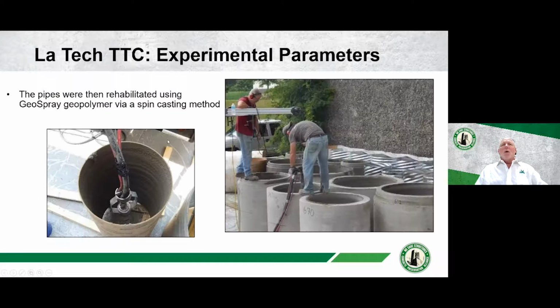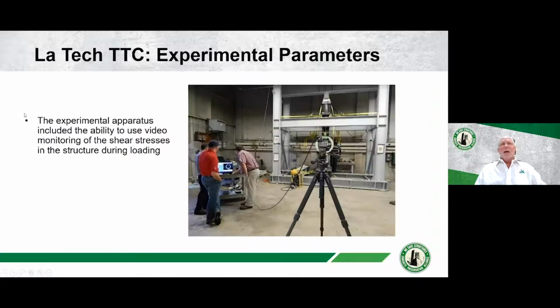In this case, a whole variety of different configurations were set up. Tests were done on reinforced concrete pipe. Some tests were done on corrugated metal pipe. So all of those samples were spin cast using the same method as would be used in the field. Different thicknesses of lining were created on different sizes of pipe, and all of those were tested in the lab in what's called a D-load test. See the configuration here. It's actually a very standard test that's done for concrete pipe. It applies a load at the top of the pipe, has a support at the bottom, and as you load it up, eventually it will break the pipe.